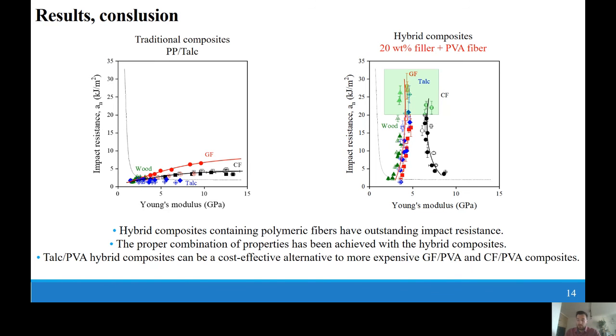I mentioned at the beginning of my presentation that our goal is to prepare composites that have both large impact resistance and stiffness. In the figure on the left, the impact resistance of traditional composites can be seen as a function of stiffness. It is visible that large impact resistance could not be achieved with these composites. The figure on the right shows the results of the hybrid composite. With the addition of the polymer fibers, outstanding impact resistance was achieved.